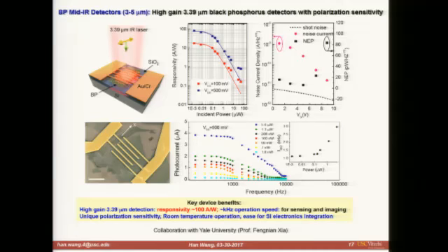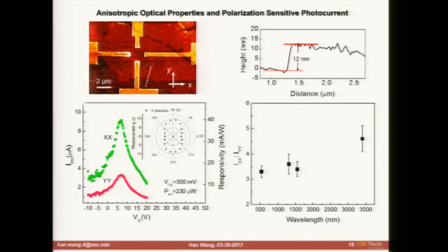The black phosphorus detector also gives the added benefit of unique polarization sensitivity. Because the material has very different optical responses along different crystal directions, incoming light polarized along the x direction versus the y direction of the crystal will give very different photocurrent in the detector. So the detector won't just tell whether there's incoming light or not, but will also tell you how it's linearly polarized.